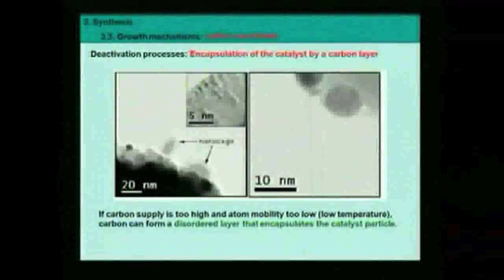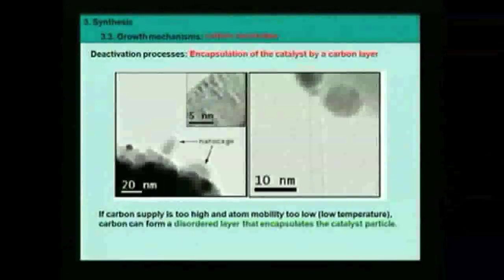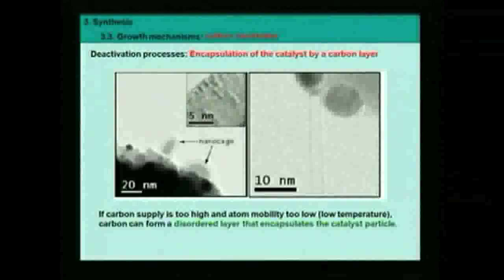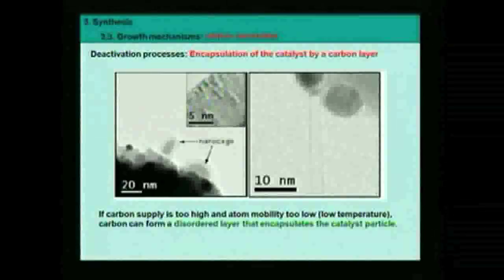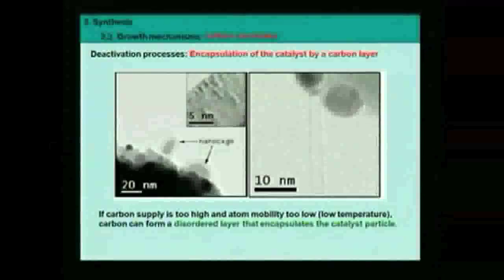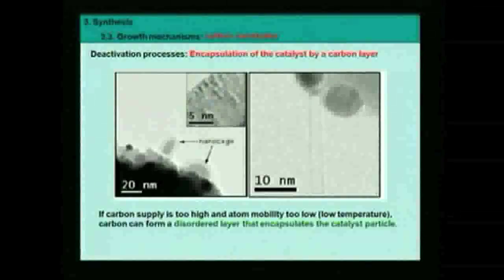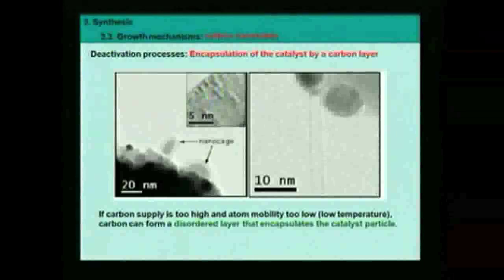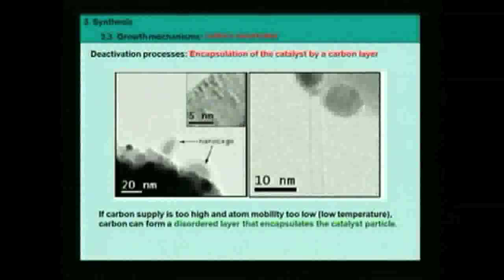It means you should use a partial pressure of carbon precursors quite low, not too high. At the same time, you should promote the fast mobility of carbon atoms at the surface. How would you do that? How would you improve the mobility of atoms at the surface? When a reaction does not go fast enough for you, what do you do? When los arepas are not cooked enough, what do you do? You increase the temperature. That's the same.